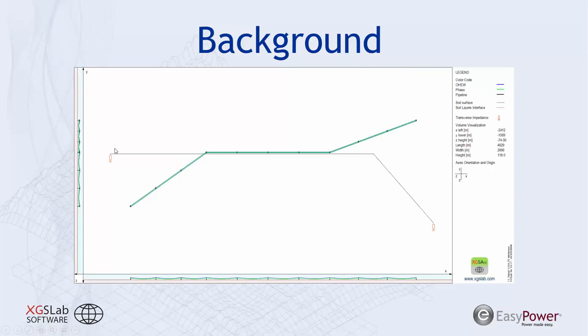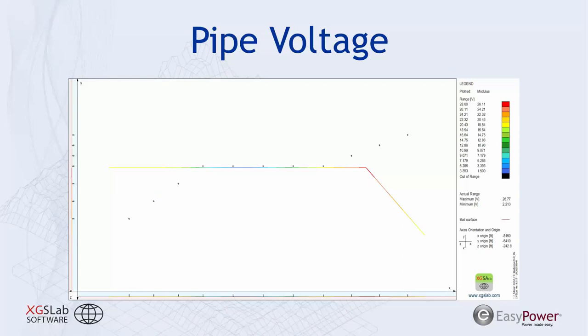For example, if you were to simply end the pipeline at these segments, you would see an artificial increase in that pipeline voltage because it just ends in your model. But in reality, it continues on to an extent that is insignificant to the analysis itself. So here's kind of our base case. We have approximately 26 or 28 volts as the maximum induced voltage upon the pipeline. And this is a concern, especially if there are any appurtenance in the areas where we have these elevated voltages.